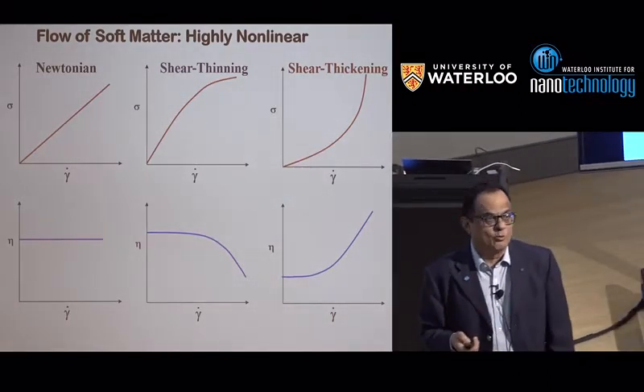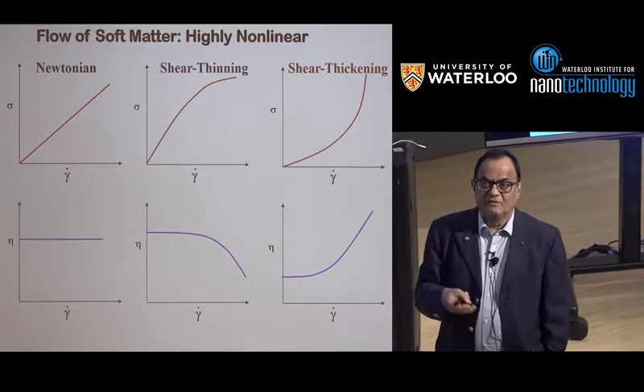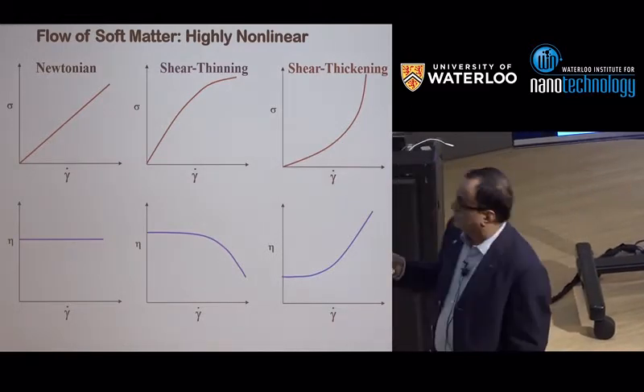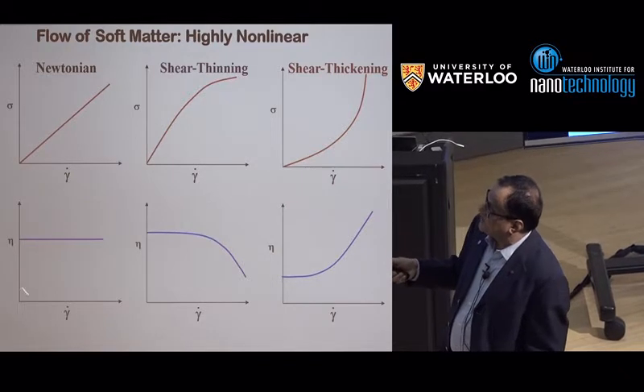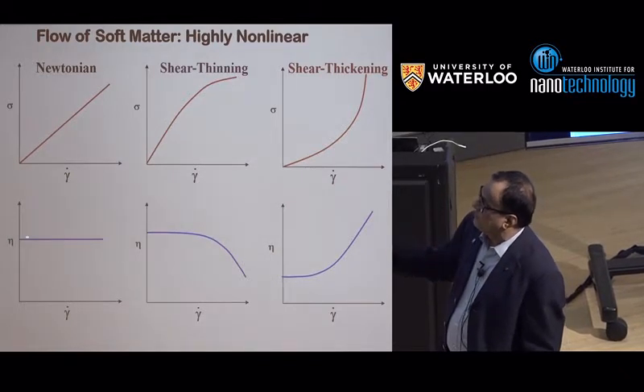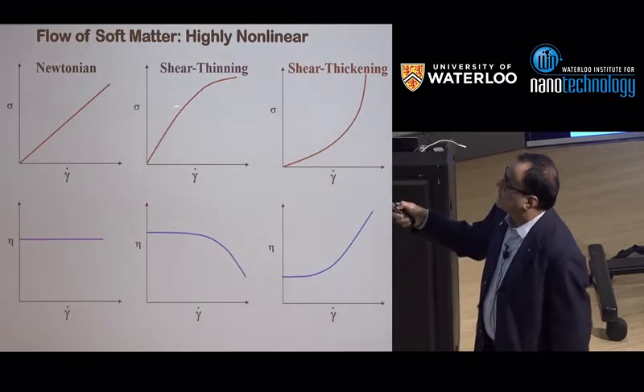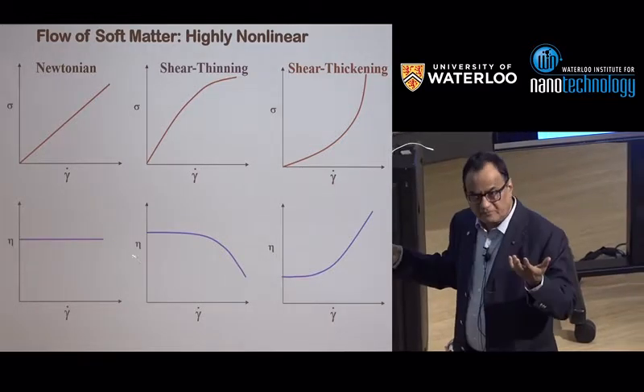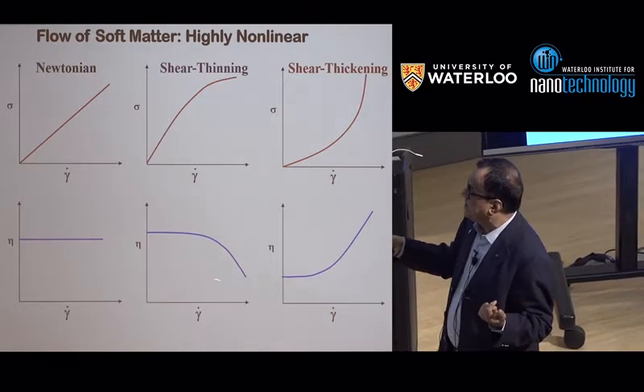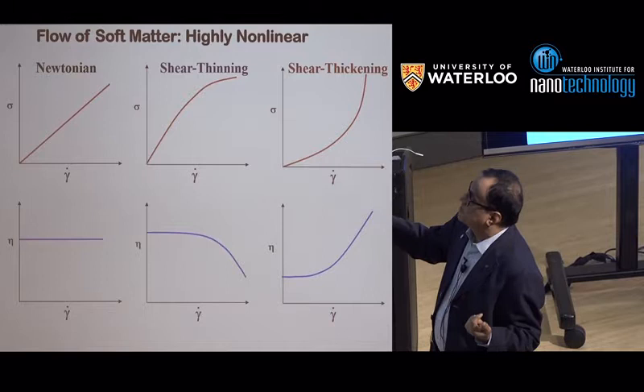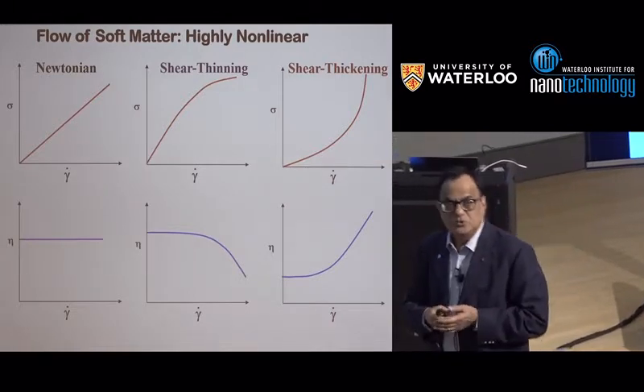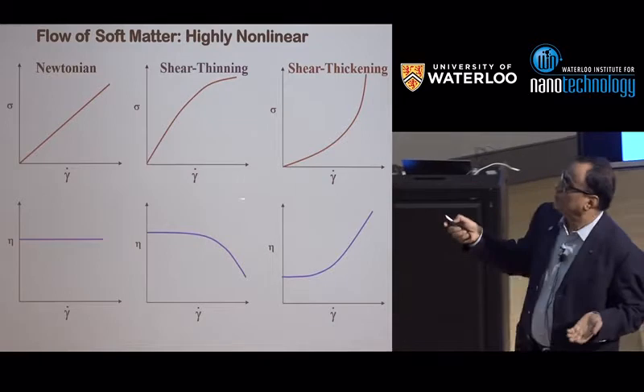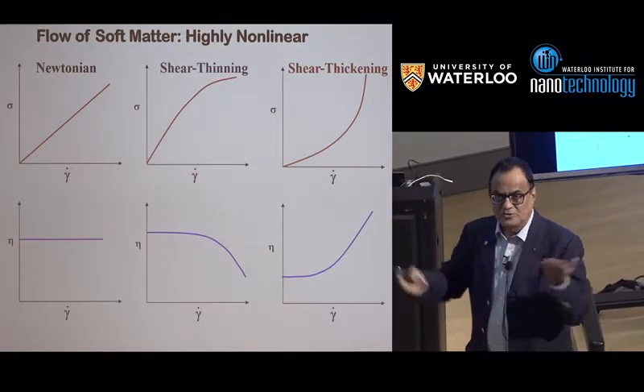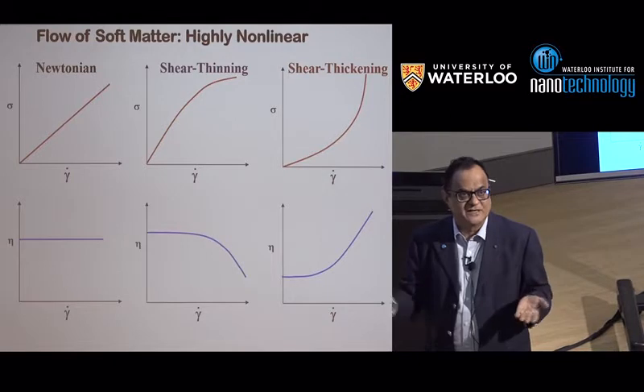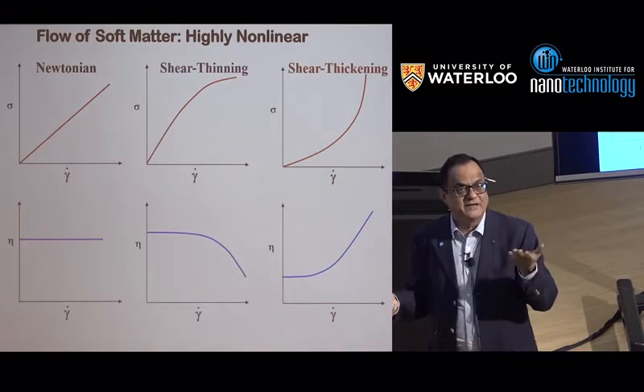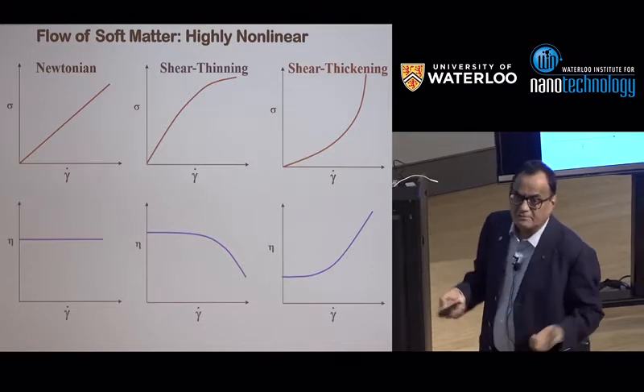Another activity in our group is to understand the flow of soft material, which is again a very popular topic. Just to remind you, if you plot viscosity versus shear rate for a Newtonian fluid, it is independent of gamma dot. But if you have a viscoelastic soft matter, the viscosity can decrease at high gamma dot or it can increase, which is called shear thinning and shear thickening. And huge billion-dollar industries are based on shear thinning and shear thickening because all your cosmetics and so many other industries depend on that. And the cement industry is hugely affected by shear thickening.